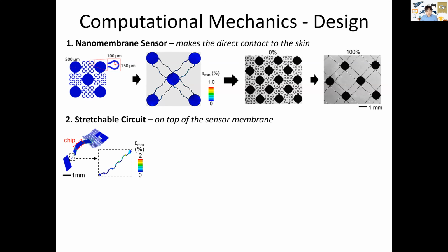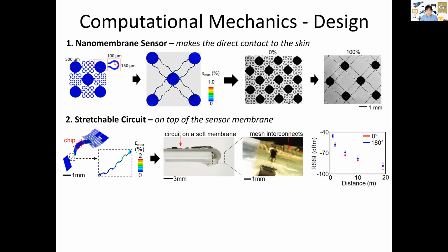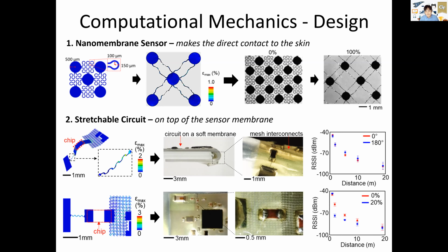However, we wanted to make sure of a fully functional device during use. So as you can see, this circuit is fully bendable, up to 180 degrees with a radius of curvature of only 1.5 millimeters. And when you measure the wireless signal quality, it maintains the signal strength up to 20 meters with bending. At the same time, the system is also stretchable. So it can endure stretching up to 20% or over 20%. And as you see at the bottom right, it's maintaining the signal quality with stretching as well.